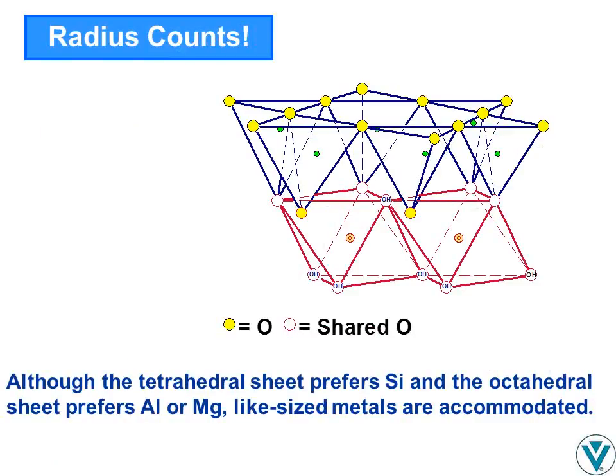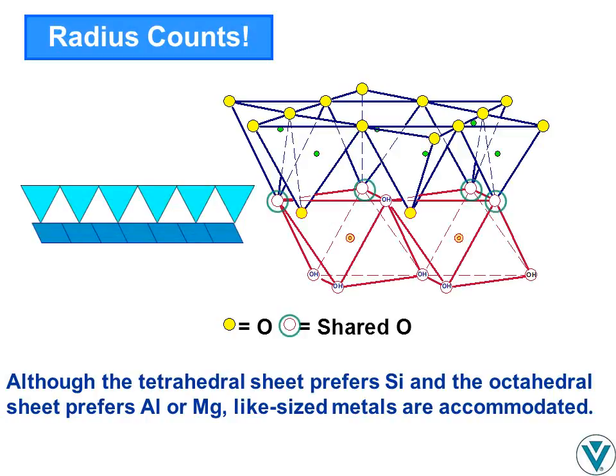The phyllosilicates and related minerals can be pictured as the joining of an octahedral layer to one or two tetrahedral layers via shared apical oxygens. While sharing these common structural features, the phyllosilicates and related minerals are differentiated by substitutions within the basic lattice configurations. This depends on how well a metal ion will fit among close-packed oxygen ions, which is largely a matter of relative ionic radii. The preferred or most stable coordination of metal cations common in silicate minerals has been calculated and expressed in terms of ionic radius ratio.